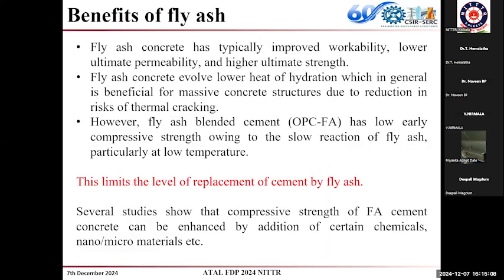Now coming to the benefits of fly ash, because it has spherical particles, it improves workability and permeability. The size of the particles provides good permeability to the concrete. And when we go for mass concreting, when we add water to cement, it is an exothermic reaction and it generates a huge amount of heat. In that case, the incorporation or replacement of fly ash in the cement helps in reducing the heat of hydration.